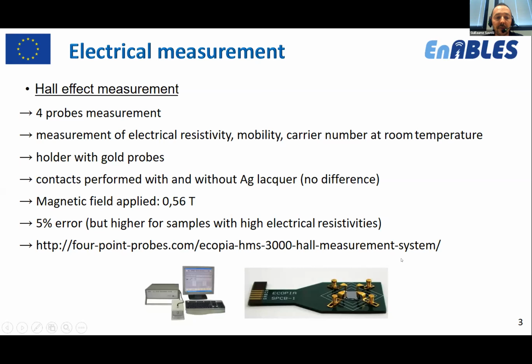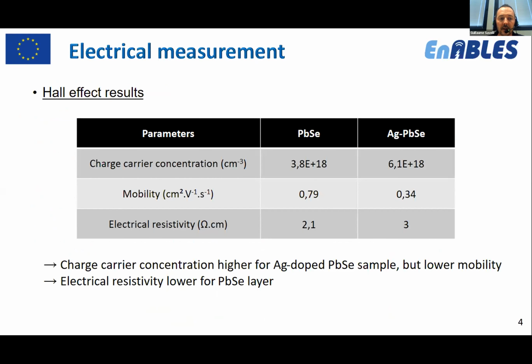Electrical contacts are performed with or without silver lacquer, but in this case, there was no difference. We applied a magnetic field, and generally we obtain 5% error in measurement. It can be a little bit higher for samples with high electrical resistivities. So for these samples, you can see here the Hall effect results.